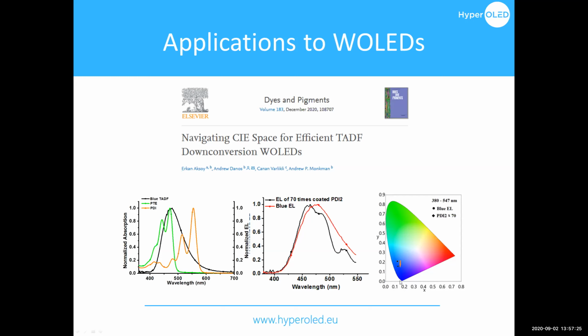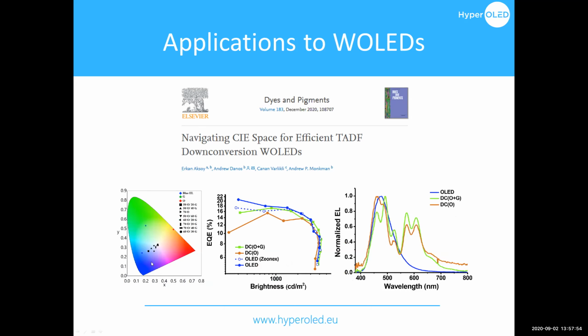Now, this doesn't normally happen in LEDs where you mix things together inside the LED, because then there's either Förster or Dexter transfer, which quenches the energy donor's peak entirely rather than selectively. But we weren't doing that. We were just relying on emission and reabsorption by the perylene itself. But what we were able to do was apply some of the green perylene that he'd prepared as a sort of course correction through CIE space.